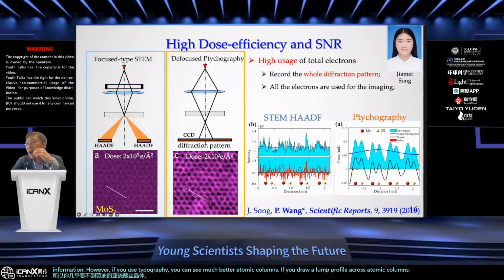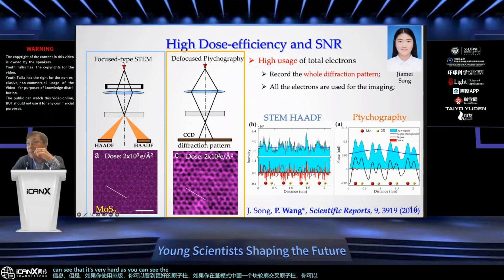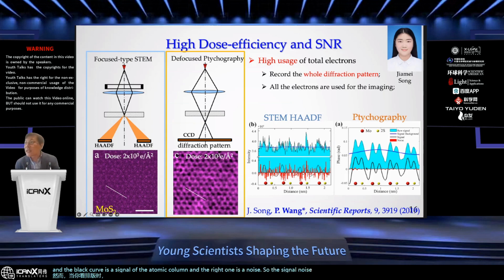it's very hard. The black curve is the signal, and the red curve is the noise. So the signal-to-noise ratio in STEM is about 1:1. However, when you look at the ptychography, the black curve is the signal of the atomic column, and the red one is noise. So the signal-to-noise ratio is about 30, which means using the ptychography reconstruction method, you heavily increase the signal-to-noise ratio.